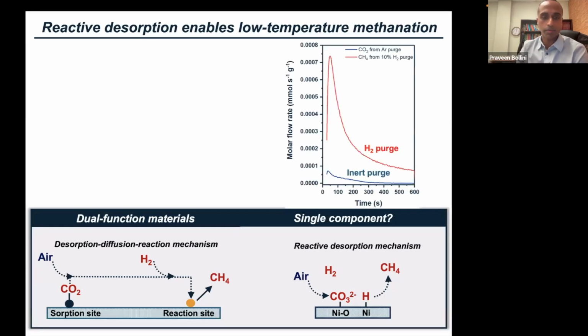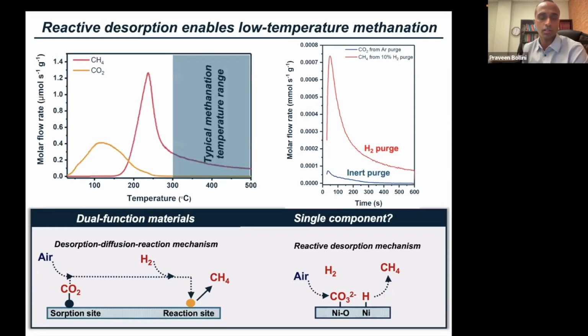So I'll just show you maybe a couple of data sets here. As you see, when you expose it to an inert purge, you don't really lose any of the CO2 because these are not done at temperatures where you desorb CO2, but you can bring in hydrogen and really convert the carbonates to a hydrocarbon species. And at least in the context of methane, which I again will emphasize is not a useful product to produce from a CO2 capture and conversion application, you're able to move the methanation temperature range to much lower temperatures than has been done previously in the literature. So if you look at a typical carbon capture and methanation reaction that's occurring at about 300 degrees Celsius, you're able to move the temperature at which you form methane by 50 to 100 degrees Celsius, which is quite a significant delta T.